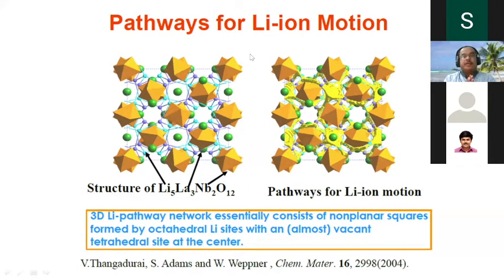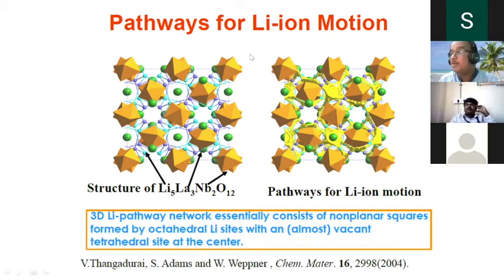It's okay. So this is the structure of the lithium. So just based on the available powder X-ray diffraction. This group is very good in this bond valence analysis. So with the available structural powder X-ray diffraction, they were able to predict, very interestingly, that it's a 3-dimensional path. It's not like a LISICON, 1-dimensional pathway for the lithium ion. It's 3-dimensional. So this is really what people want. So a lot of interest came to the garnet.